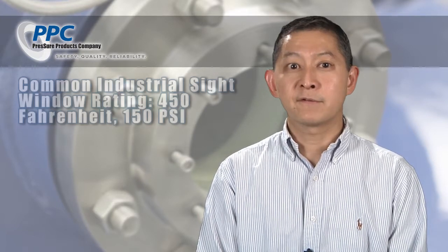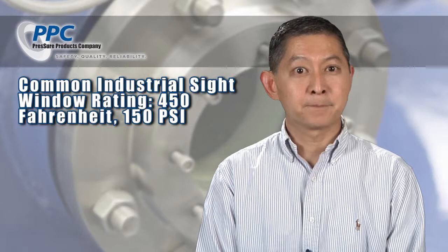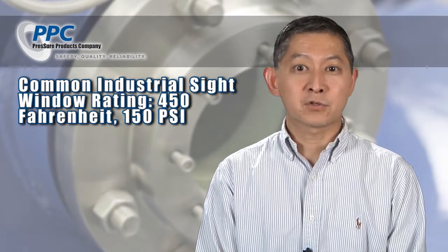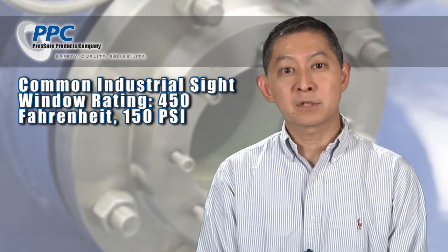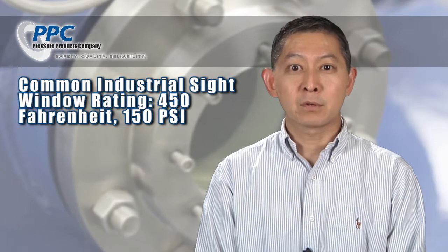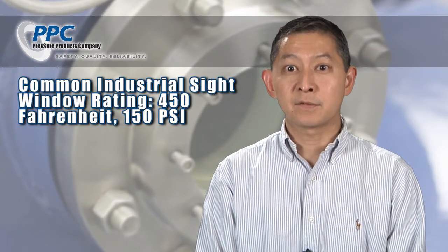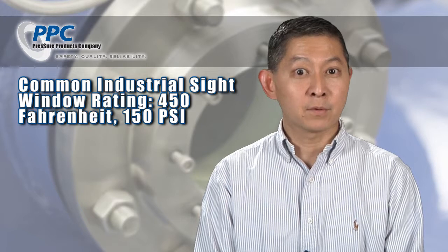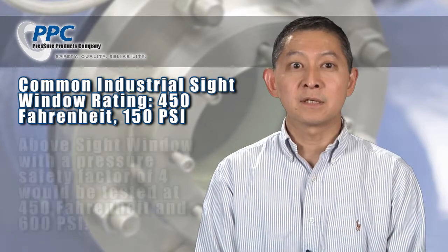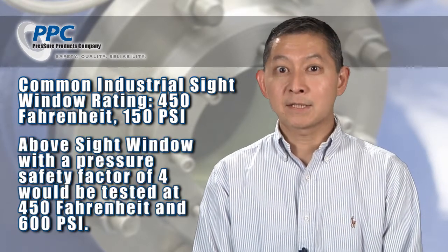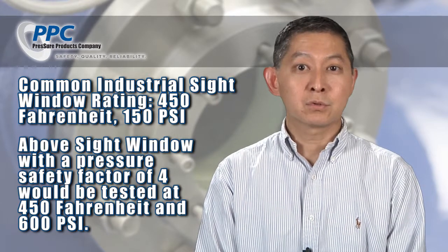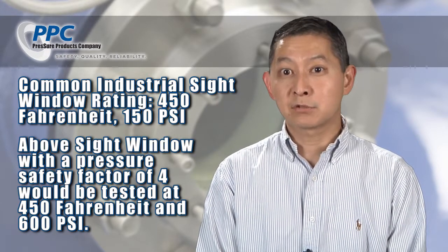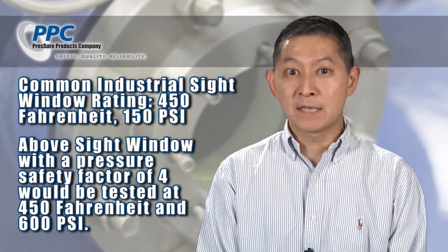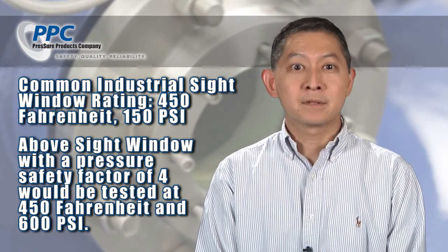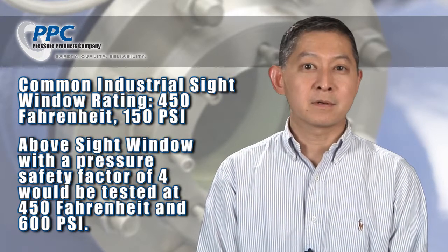A lot of commercially available sight glasses are rated for 450 Fahrenheit at 150 psi. Sight windows' pressure safety margins are rated and tested at their maximum service temperature. So a sight window rated for 450 Fahrenheit and 150 psi with a pressure safety factor of 4 would be tested at 450 Fahrenheit at 600 psi. The usual rule is that at the max pressure, 600 psi, the sight window may leak, but it must not burst. Now that sounds good until you think about it a little.